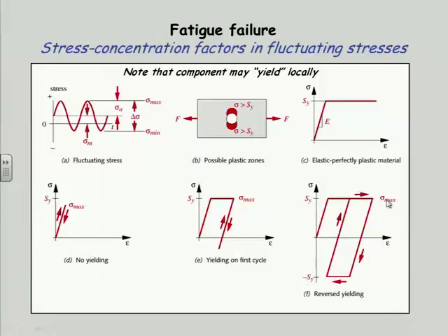Because now, if I make the K factor for the mean stress 0, then the mean component goes to 0 because I multiply it by the stress, right? And that, in effect, is a fully reversed case. So if I am exceeding the yield point on the upstroke and the backstroke, tension and compression, my mean stress is 0, isn't it? So then I'm back to a fully reversed case. So we're going to have 3 possible values for what's called KFM, K fatigue mean. And it'll either be full value of the KF, whatever that turned out to be, or it'll be somewhere between 1 and that value, or it'll be 0.